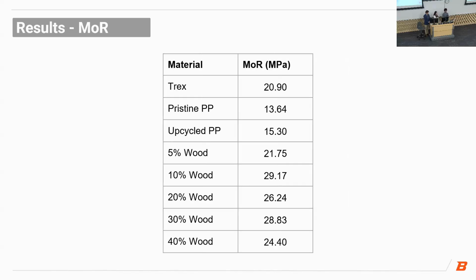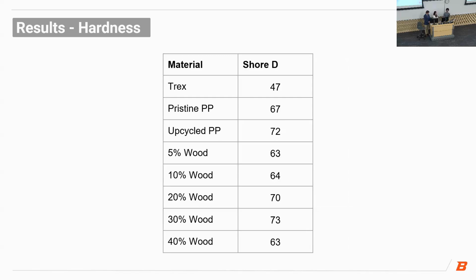There's a modulus of rupture, same trend occurring. That dip occurs after the 30% into the 40%. And the hardness testing, not too much that's different across all of the samples that we manufactured. There's a noticeable hardness difference between the industry standard Trex and our samples.